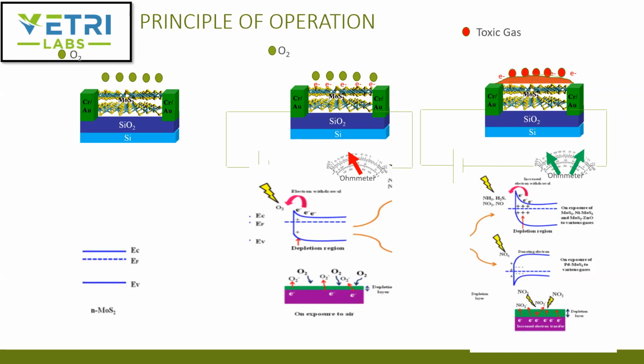And if you supply a toxic gas in addition, it depends if it is either an oxidizing species or a reducing species. If it is oxidizing, again, it will increase that electron withdrawal above what you have with the oxygen in air, and that will change the resistance of the circuit. So if you have air and then you have toxic gas in air, that should give you a clear signal between the resistance of just bare, pure air, and the resistance with a toxic gas in air.